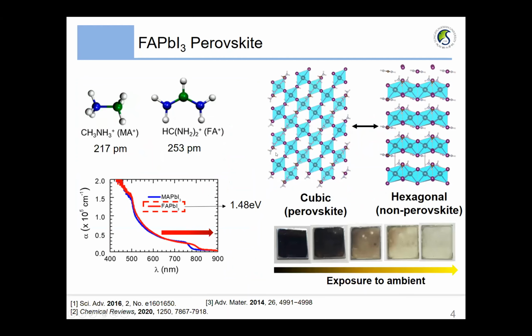Okay, so recently, among the perovskite materials, the formamidinium lead iodide, or FAPbI3, perovskite has been widely studied because of its exceptional band gap close to the ideal value for single junction cells. The FAPbI3 has two major phases, hexagonal and cubic phase, also called the delta phase and the alpha phase. By annealing at high temperature, the delta phase converts to the alpha phase, becoming the photoactive state.